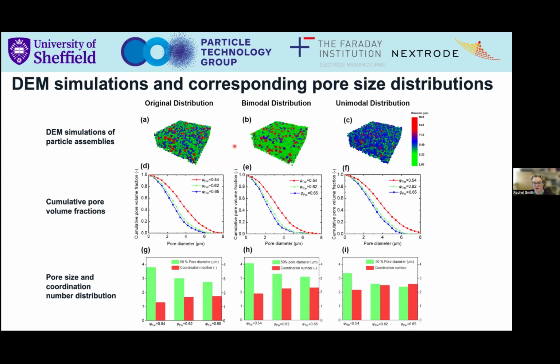We then deliberately, by maintaining the same average particle size, manipulated that distribution to give us a bimodal distribution, so that we have a lot of small particles and we have some big particles. And then we also deliberately manipulated that to give us a much tighter unimodal distribution, so all the particles are close together and there's not a big variation in the particle size.